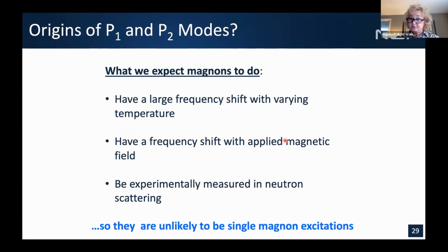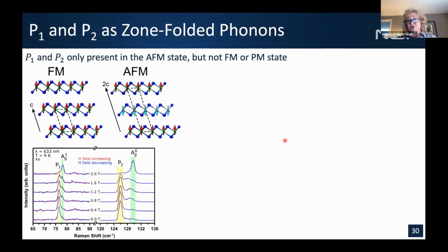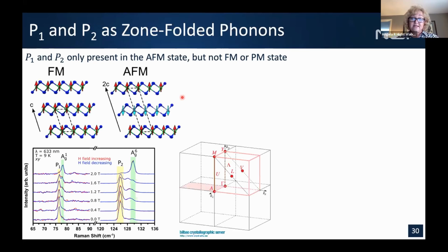So if those two features, the P1 and P2, were magnons, we would have expected to see a large frequency shift with temperature. We'd see a frequency shift and splitting with applied field, and they would have been experimentally seen in neutron scattering. And none of those things did we see. So we believe those two features are unlikely to be magnons or single magnon excitations. Instead, we believe that P1 and P2 are zone-folded phonons, much like we saw in the iron PS3. And that's because in chromium triiodide, when you go from the ferromagnetic to the antiferromagnetic case, your unit cell doubles. And by doing so, you can see non-gamma point phonons with Raman.